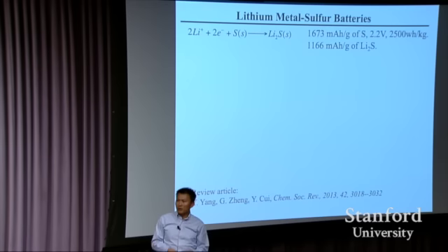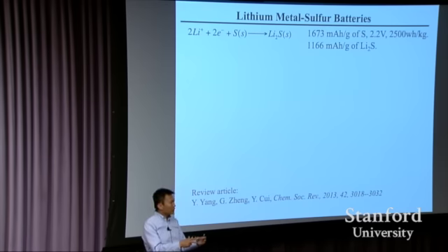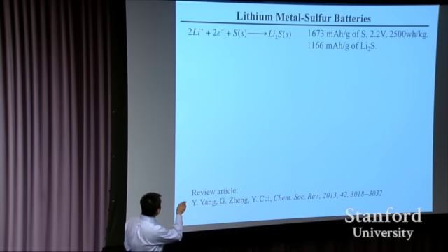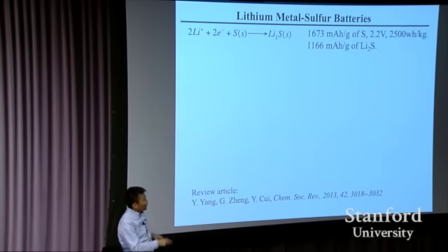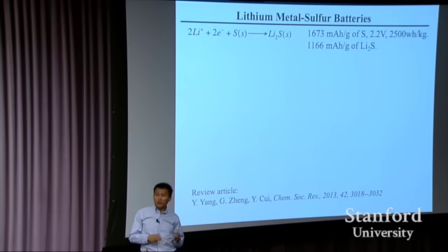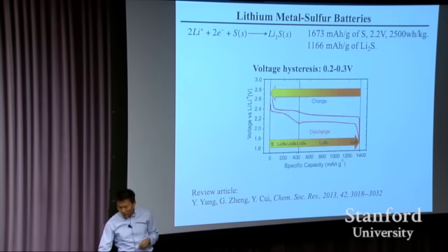So silicon is an anode. For the cathode, I'm going to move quickly to really show you it's possible to have the next generation of high energy batteries. In order to have the full battery energy density go very high, sulfur is very attractive. Sulfur has a 1700 milliamp hour per gram capacity, 10 times that of lithium cobalt oxide. The voltage is half. So you are talking about energy that can get to four to six times the existing battery technology, very attractive.